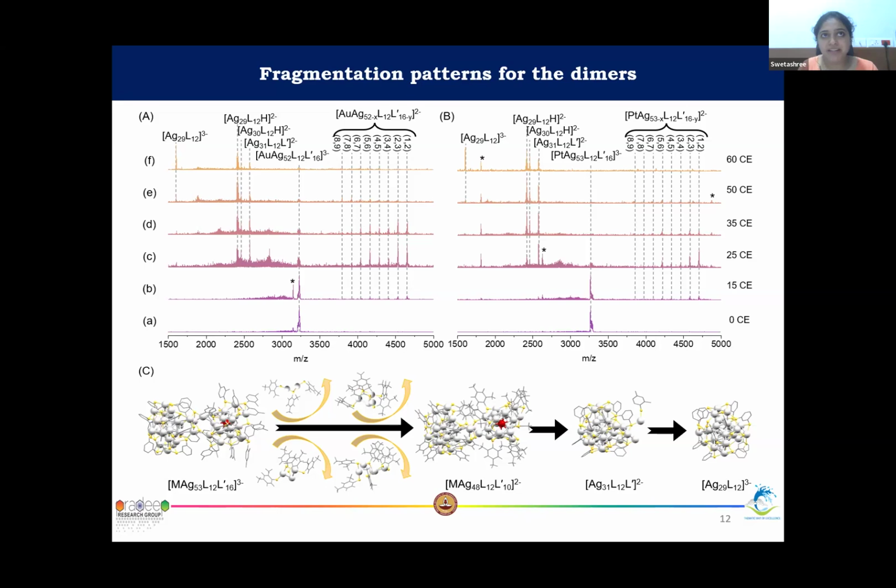Pollutants will be reduced at lower concentrations, but... Very good. And maybe we can use different cations. And lower temperatures, Swetashree. Lower concentration, lower temperature, whichever reduces the kinetic energy. In solution, the kinetic energy is nothing but related to temperature, diffusion, essentially.